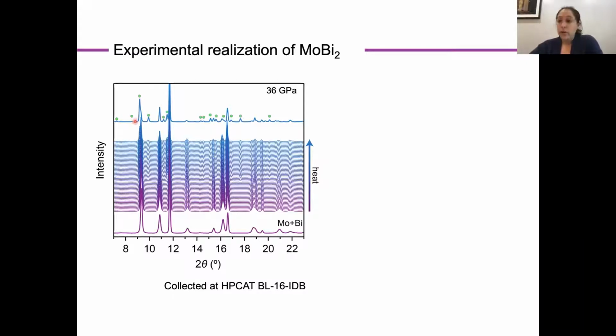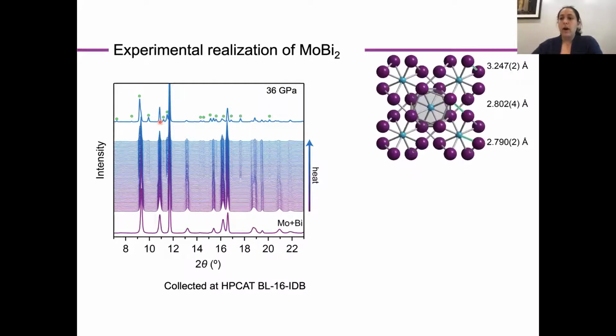And so we can look at these new peaks and index them to suggest a unit cell, compare that unit cell with the literature to come up with a model, and refine against that model to come up with a candidate structure. And so here is the result of that Rietveld refinement. And hopefully we're immediately struck, as I was, by the similarity between this structure, which is derived from the experiment, and the computational structure I showed on the previous slide. At this point, we were quite ecstatic to realize that we had used computation to predict an experimental result.